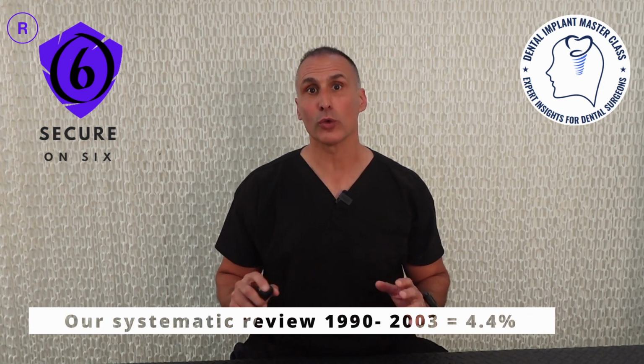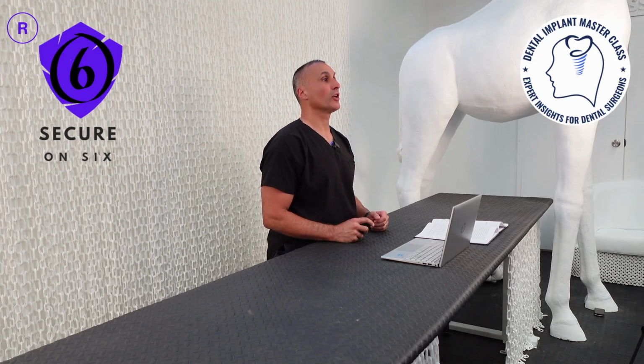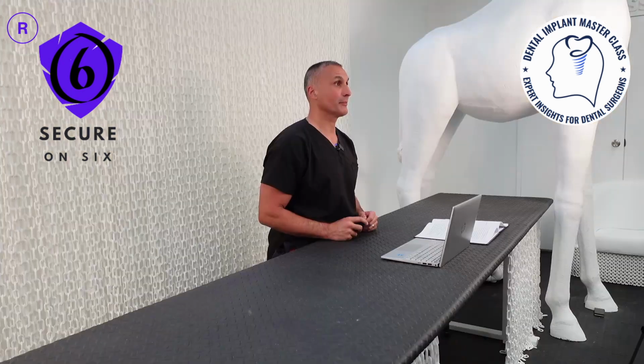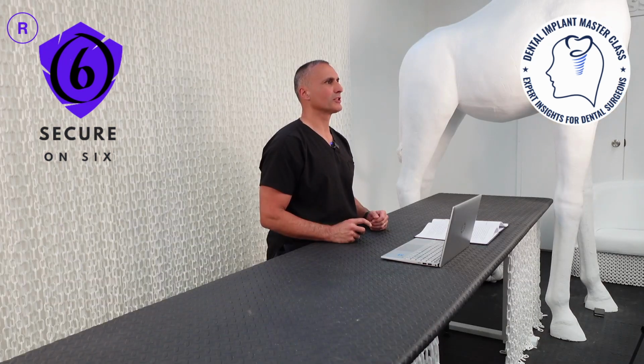In a systematic review that we performed covering the period from 1990 to 2003, the overall screw loosening rate was calculated as 4.4%. Interestingly, it was observed that the rate of screw loosening and fracture increased by 0.61% per year during this period. This indicates that despite advancements in screw design, clinical complication of screw loosening and fracture has not improved significantly. Historically, the Brånemark concept used gold alloy abutment screws. However, nowadays, manufacturers are increasingly offering and using titanium abutment screws due to their cost effectiveness. Some manufacturers have even exclusively included titanium abutment screws in their catalogs.